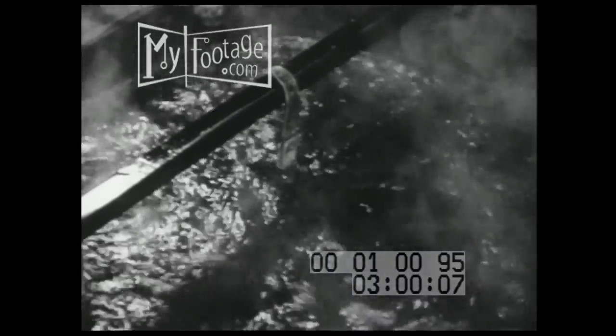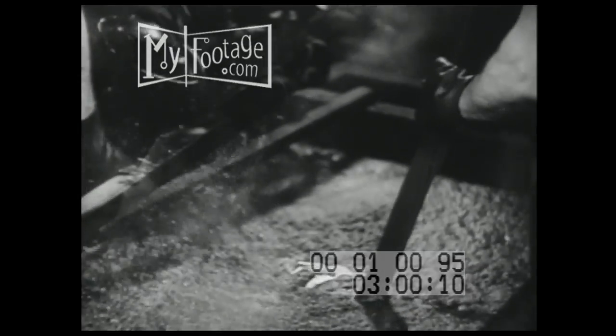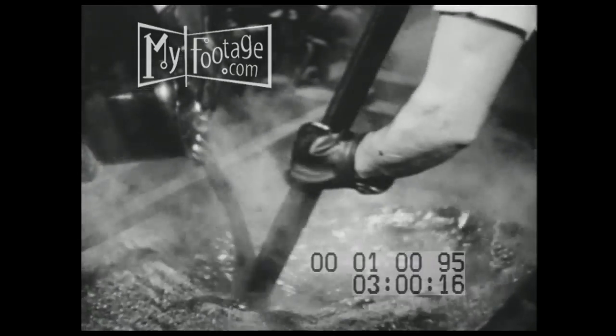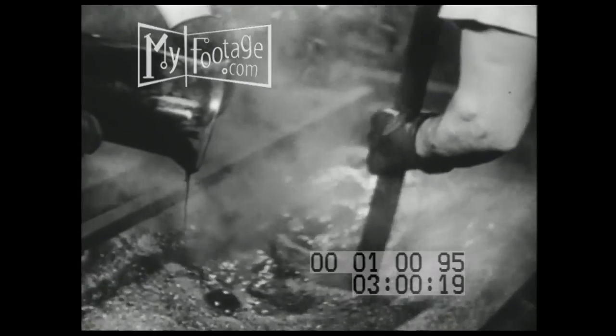This absorptive characteristic can be an advantage. If before sealing the coating is dipped in a dye solution, it takes on color just as cloth is dyed — the dye actually becomes part of the coating. A resist was used on the areas which were not to be colored. These colored aluminum nameplates illustrate a practical use of the Alumilite process. Alumilite finish in colors offers many possibilities in terms of beauty and practical use — for instance, colored fittings on airplane hydraulic lines for quick identification, and nameplates and easy-to-read dials.